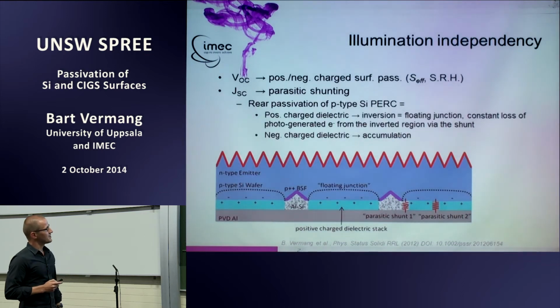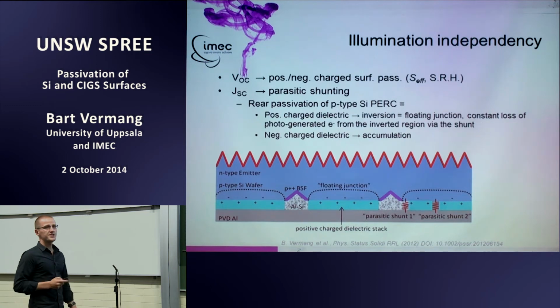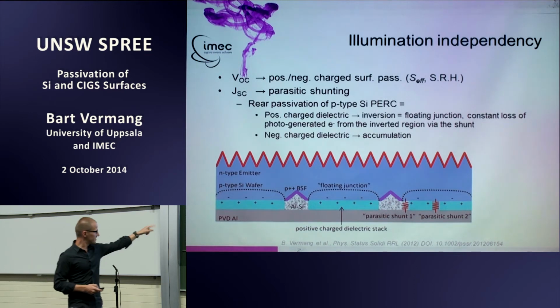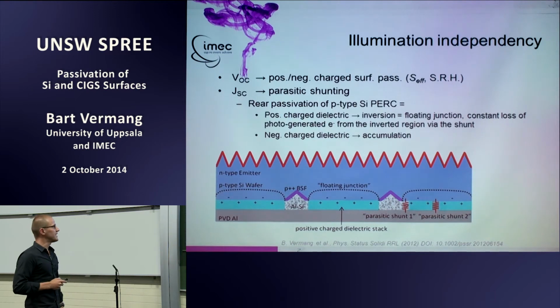Another thing that's an advantage for aluminum oxide passivated P-type cells is illumination dependency or independency. So if you look at the VOC, VOC is related to Shockley-Read-Hall recombination, and depending if you have a positively charged or negatively charged surface passivation layer, your VOC will or will not become illumination independent or dependent. If it's positively charged, your VOC will be illumination dependent. Same thing for the JSC. If you have a positively charged layer, you will create an inversion layer and not an accumulation layer at the